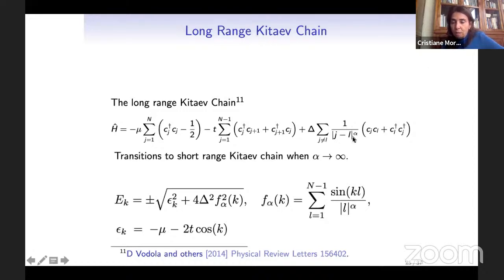It's not for alpha equal 1, because if alpha is 1, I have the same strength, this is not decaying, for all J's and L's. But if alpha is infinity, this term will drop and cut off all the pairings except when J minus L equals 1, because 1 to infinity is still 1. So actually the short range Kitaev chain, when I don't have this term, and L is J plus 1, this will only hold for alpha equal infinity, when I cut off all the other pairings.